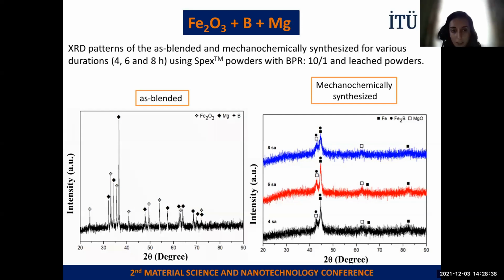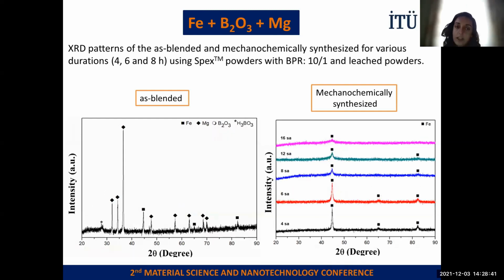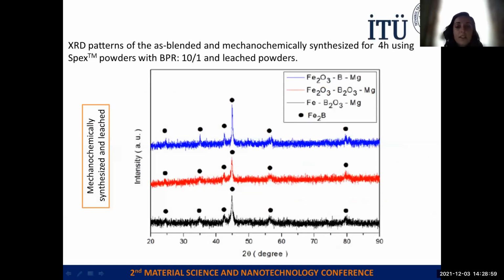And the last one is the iron, boron oxide, and magnesium batch. Again, we can see the as blended and milled powders XRD patterns for the various durations. Also here we see that our main peaks belong to the iron. And the last XRD pattern shows us that, using these 3 different routes, after the purification, we can eliminate the magnesium oxide peak from our XRD pattern, and we have only iron boride peaks, and this shows us the purified nanoparticles.